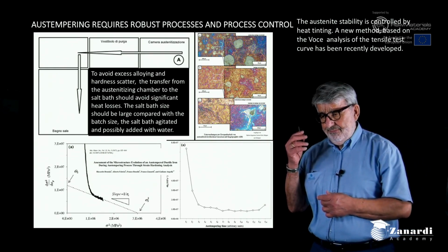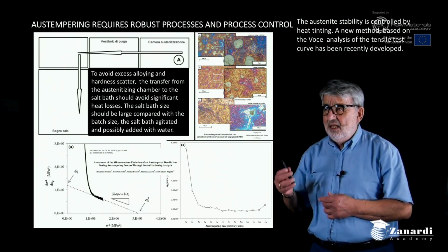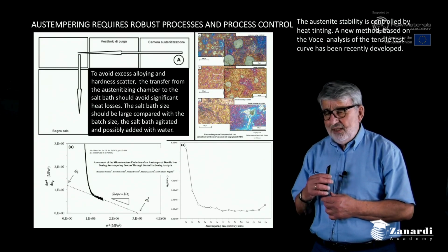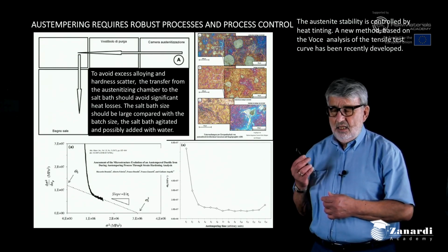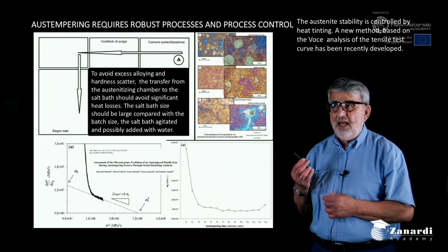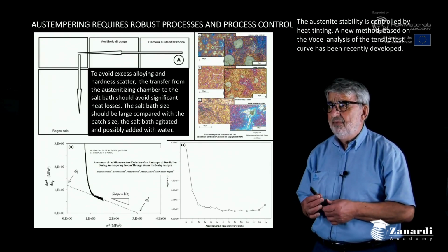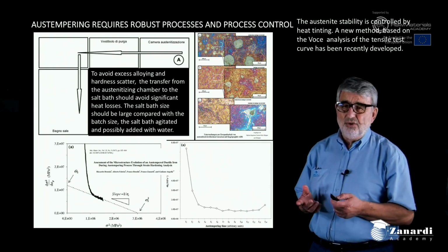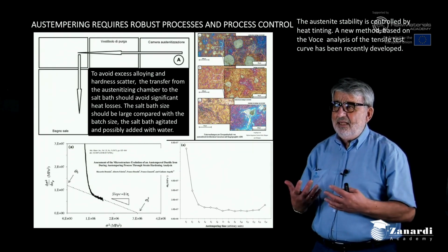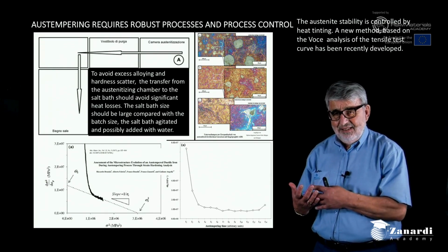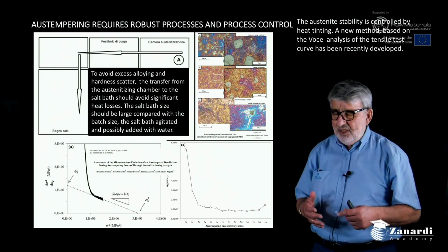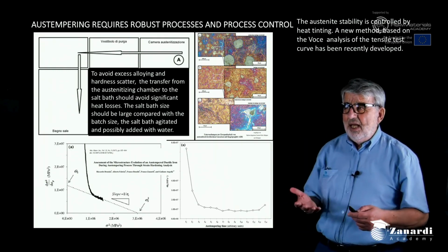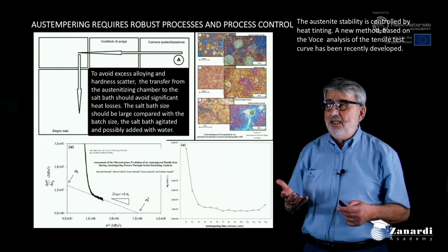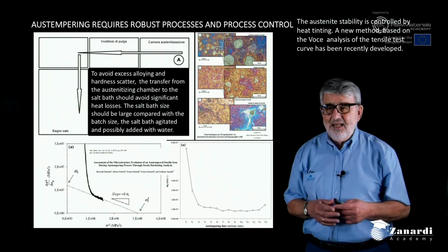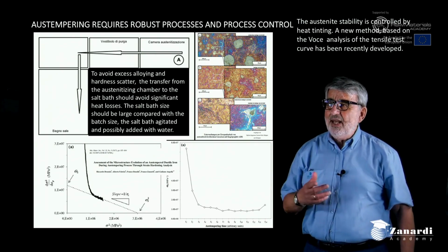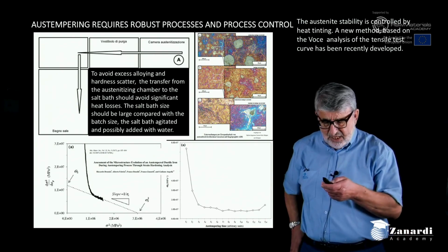If the austempering plant is not proper, it is impossible to get stable austenite and a machinable casting after treatment. Very important is also the process control that is made by tensile test, that now we analyze in a new way using Voce analysis to check the austenite stability, or traditionally with heat tinting, where the blue areas correspond to unstable austenite transformed into martensite.